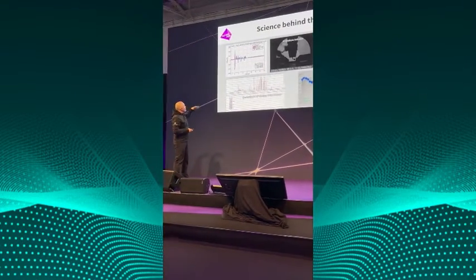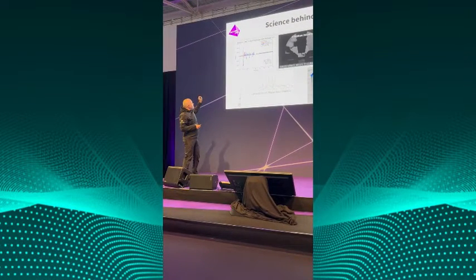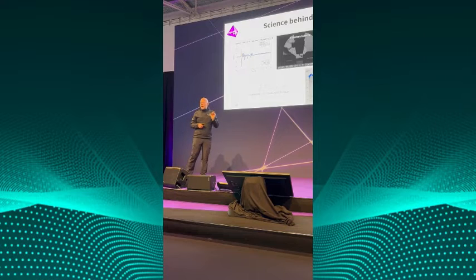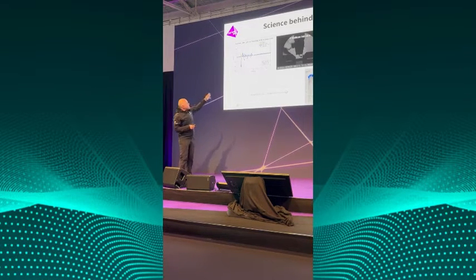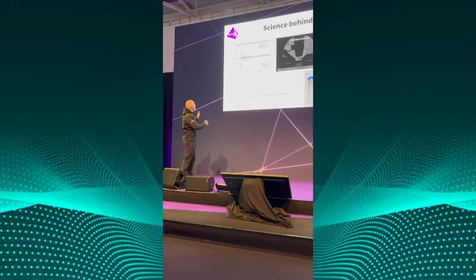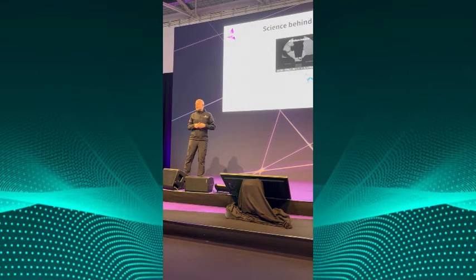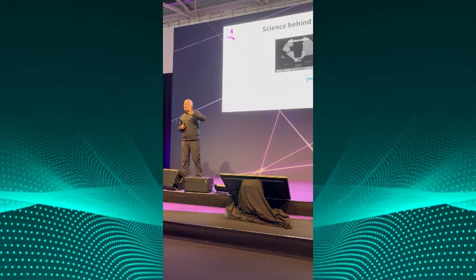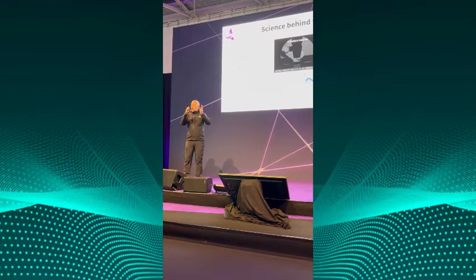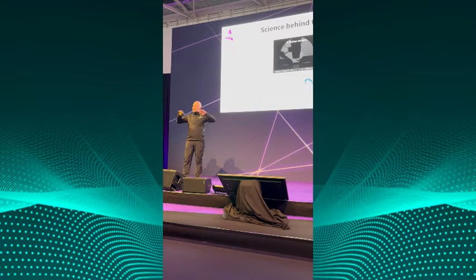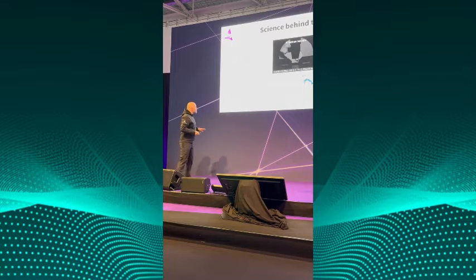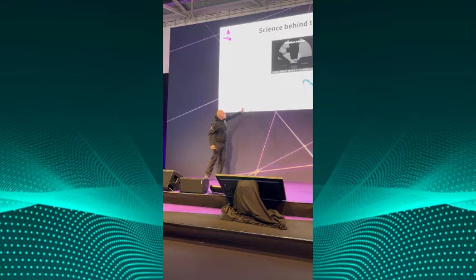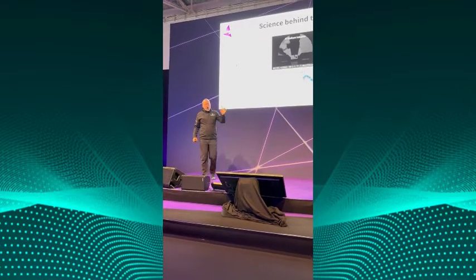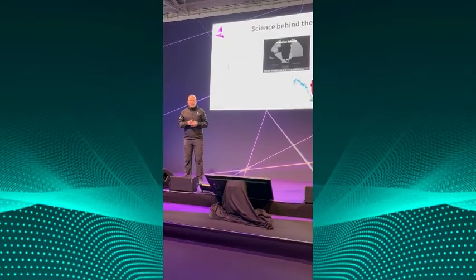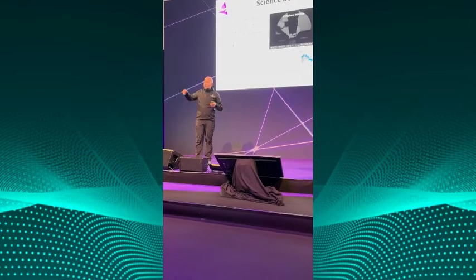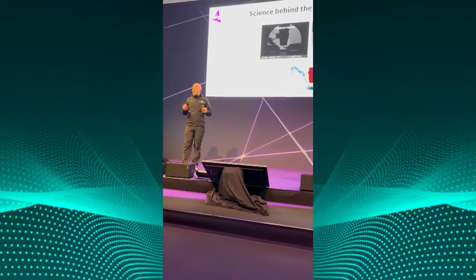On the left side, that's something very interesting. It's kind of a snapshot of an arc strike, and those are millionths of a second. So what happens in the first 5 millionths of a second? How the partial breakdown ionizes shielding gas, and afterwards how this energy is dissipated with thermal conductivity through the shielding gas. This is a detection or a spectrogram, so we can watch the arc, and just as we can watch the sun and determine what it is made out of, we can determine the composition of the plasma.